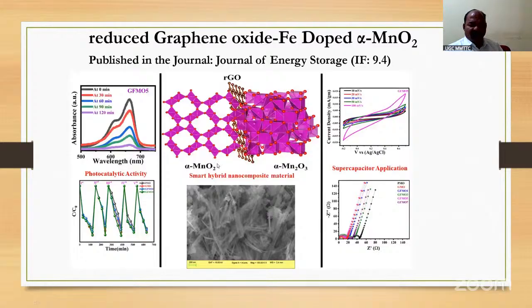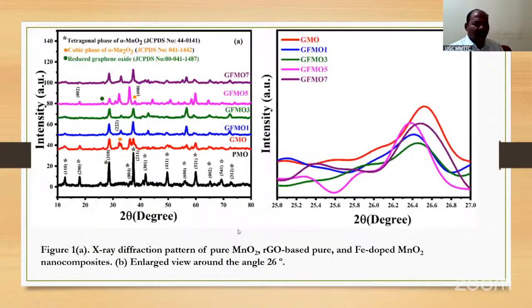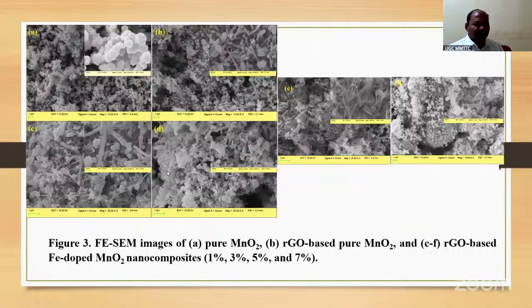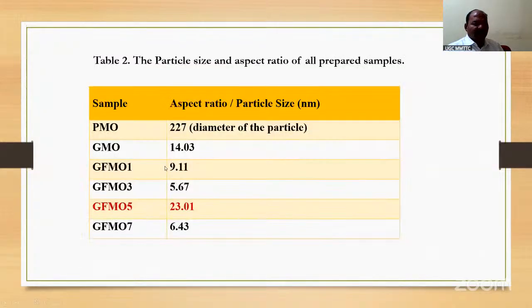Reduced graphene oxide iron doped alpha MnO2. So here are the structures of this, and you see the nanowires. These are the X-ray diffraction patterns. And these are the micrographs of the samples. The particle size and aspect ratio of all synthesized materials is given here.